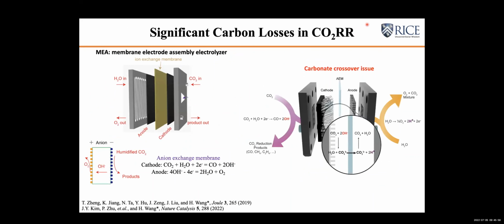I think my time is almost there, but one last slide that I want to share is the carbon loss issue that we recently discovered. So as you can see here, this is the MEA device that we demonstrated before. OH is the ion conductor, but in fact, when you do CO2 reduction on the MEA device, you generate those OH groups, pushing up a very high local pH. Those OH groups will automatically react and absorb the unreacted CO2 molecules in your gas stream to form carbonate that will cross over the membrane and then get re-acidified by the OER catalyst because you generate a lot of protons at the OER side. That will have your CO2 moving from your cathode side towards your anode side.